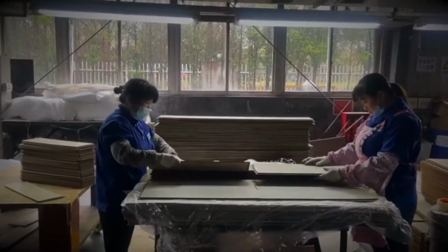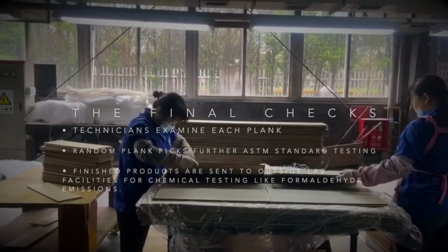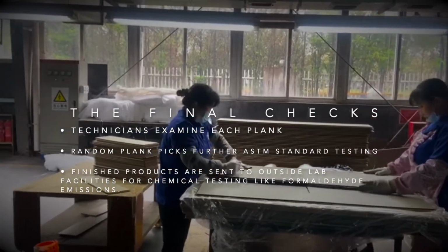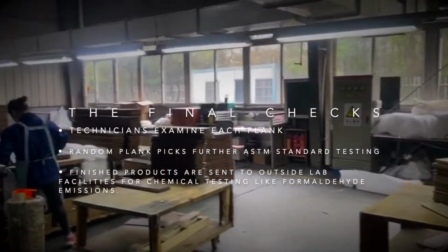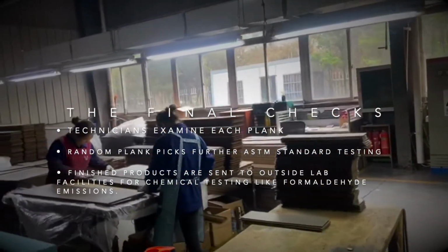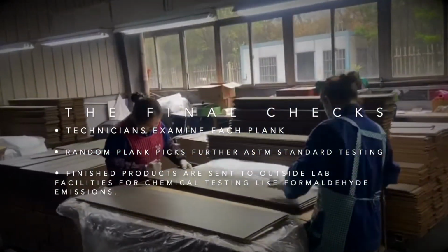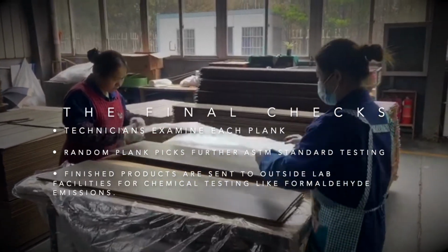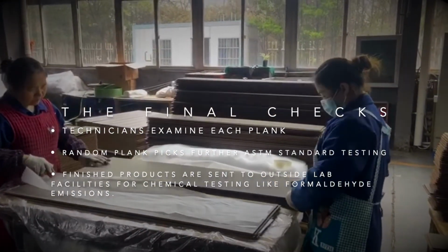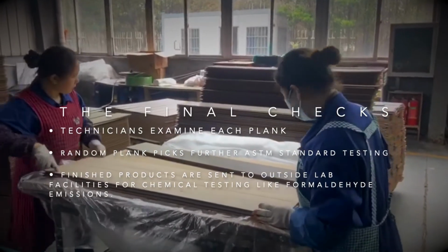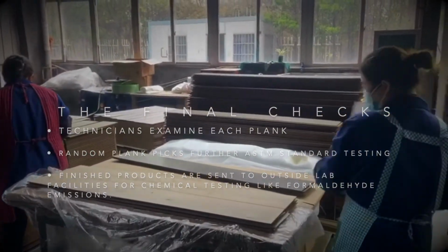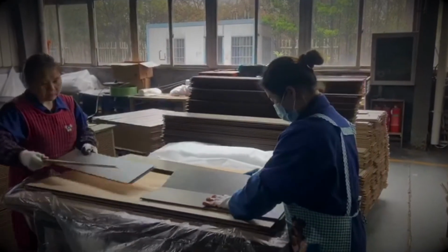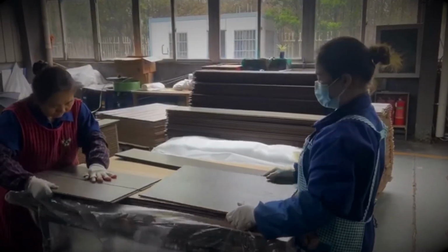Phase 11, final quality check. Technicians inspect each plank for final result. Matching plank to the master color board, coating issues like insufficient or too much, inspecting for cracking, dimensional deviation, dimensional stability like bows and cups, gloss level, moisture content, immersion peel test again to test the adhesion strength, high-low temperature cycle. We also send product to third-party labs to inspect for chemical testing and formaldehyde emission.